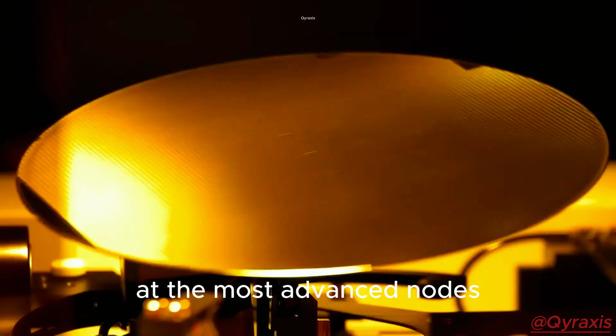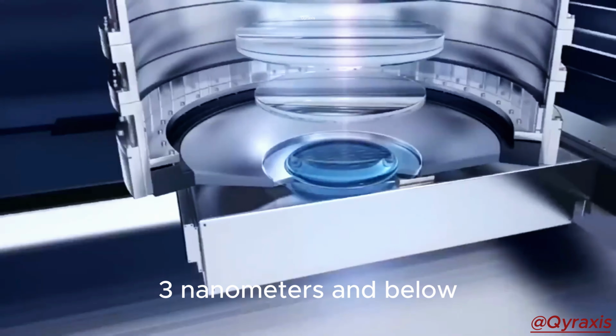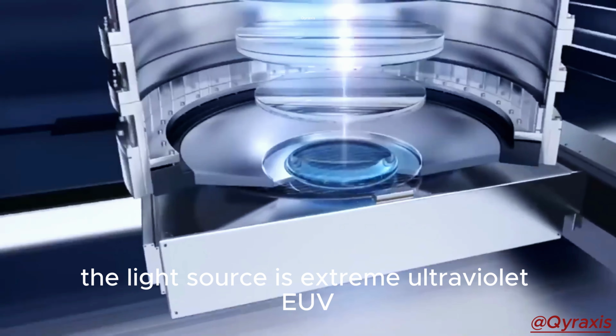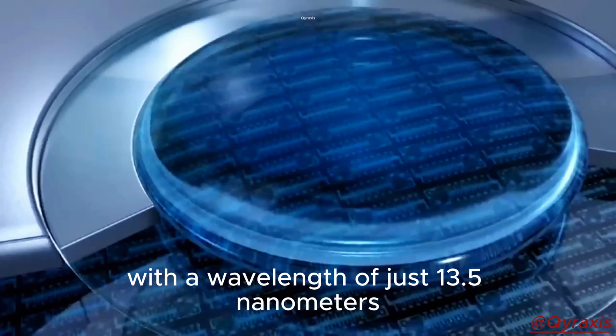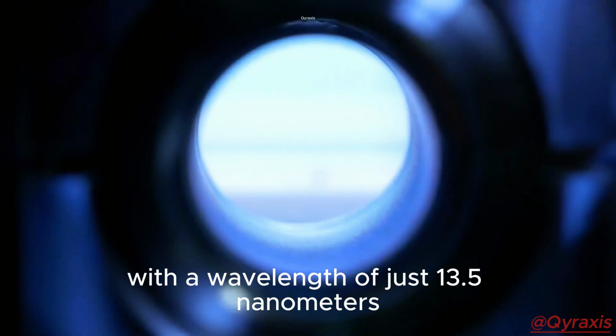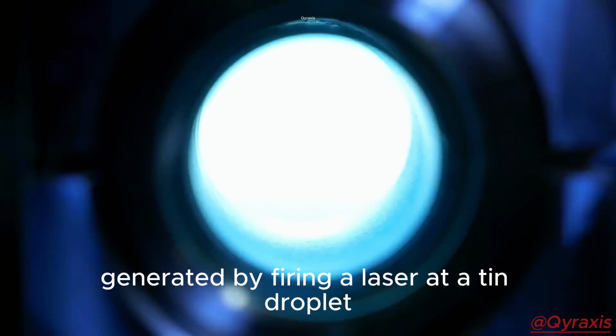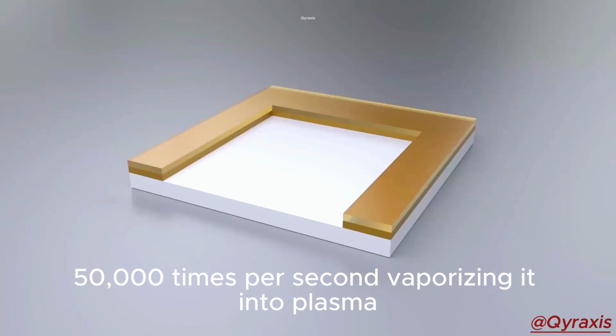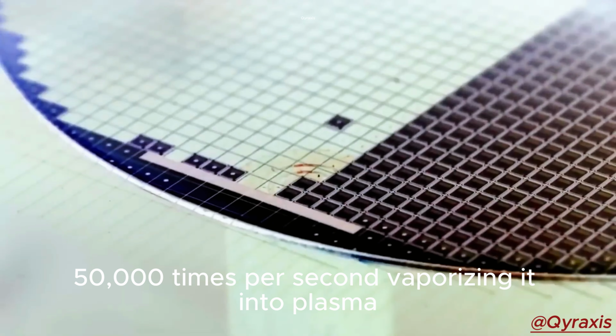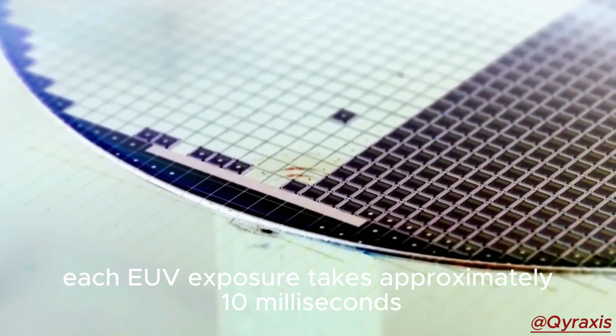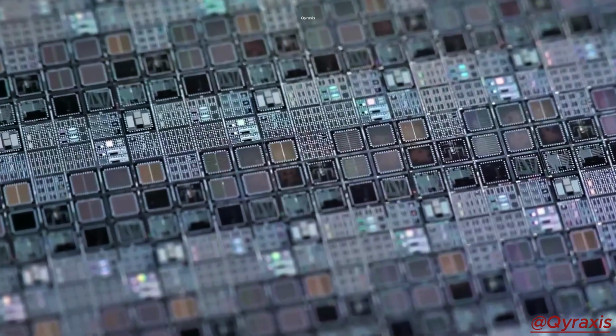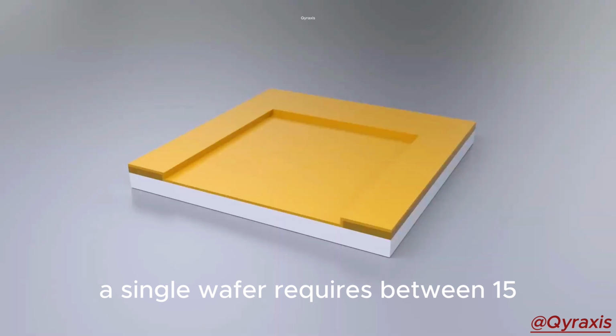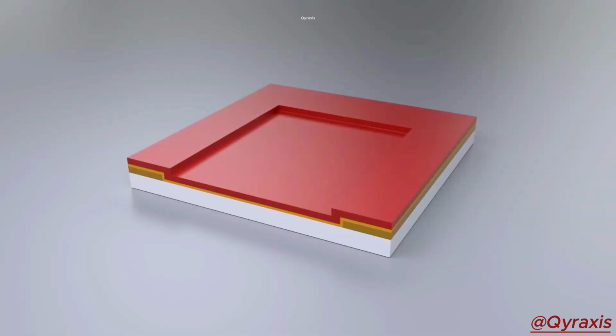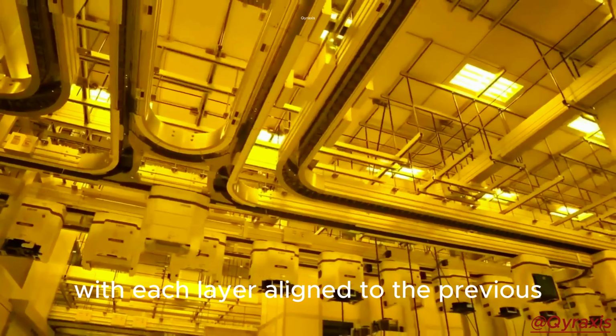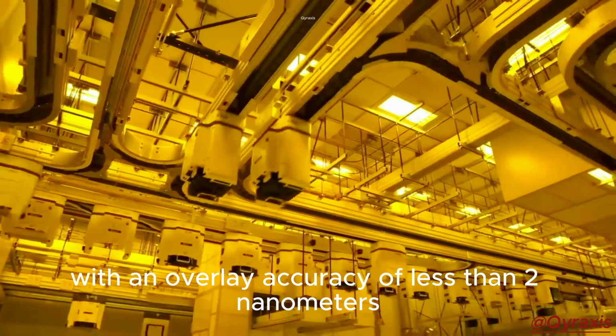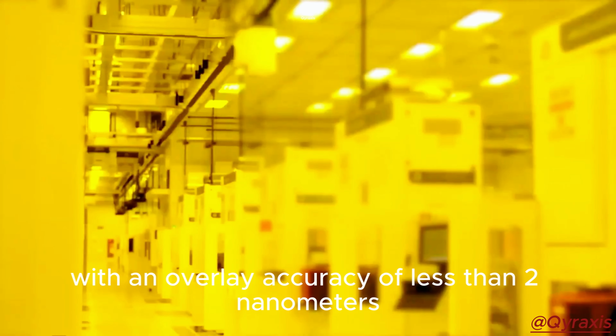At the most advanced nodes, 3 nanometers and below, the light source is extreme ultraviolet, EUV, with a wavelength of just 13.5 nanometers, generated by firing a laser at a tin droplet 50,000 times per second, vaporizing it into plasma. Each EUV exposure takes approximately 10 milliseconds. A single wafer requires between 15 and 40 separate exposures, one per circuit layer, with each layer aligned to the previous, with an overlay accuracy of less than 2 nanometers.